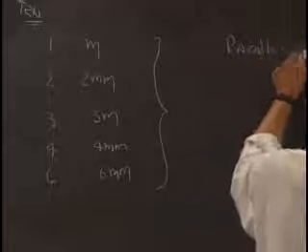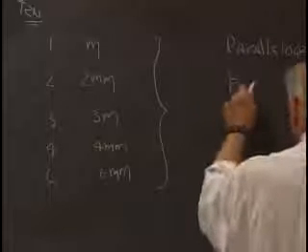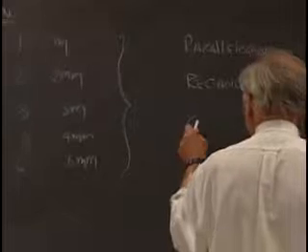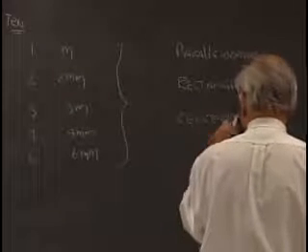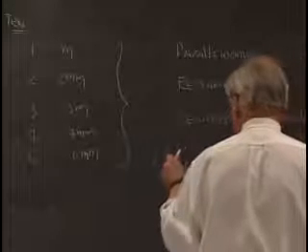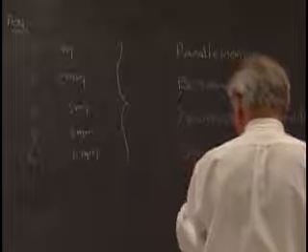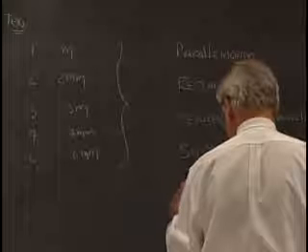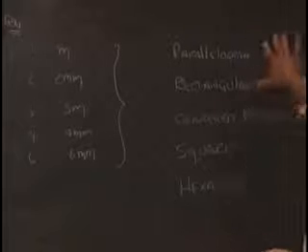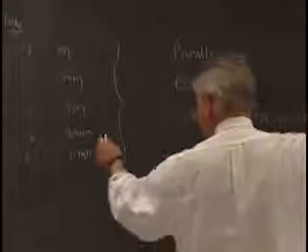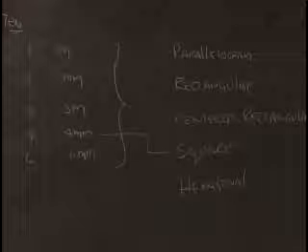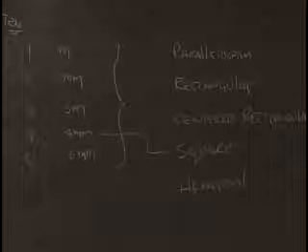the parallelogram net, the rectangular, the centered rectangular, and the square, and the hexagonal. Now clearly we can't put each of those point groups in every one of the lattices. For example, the lattice has to be square for either 4 or 4mm, so we would attempt to place only those two of the 10 point groups into a square net.